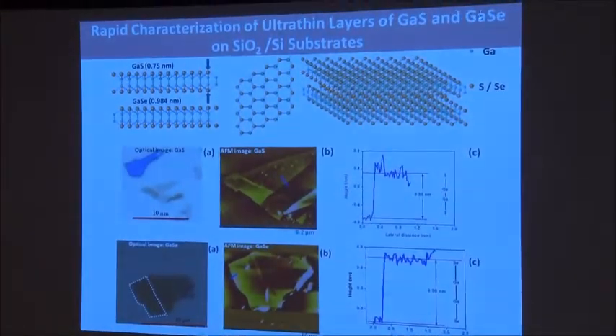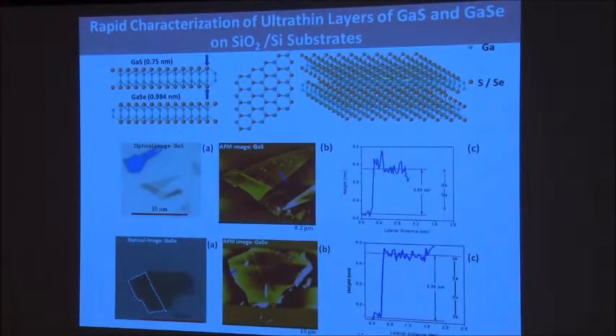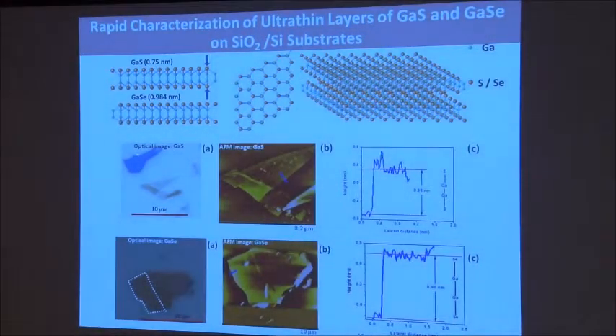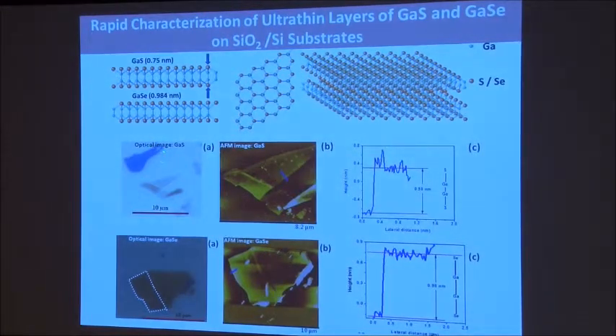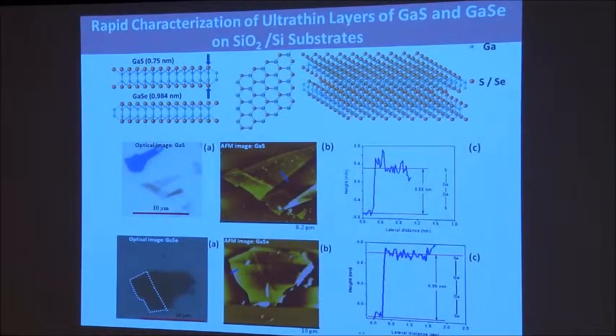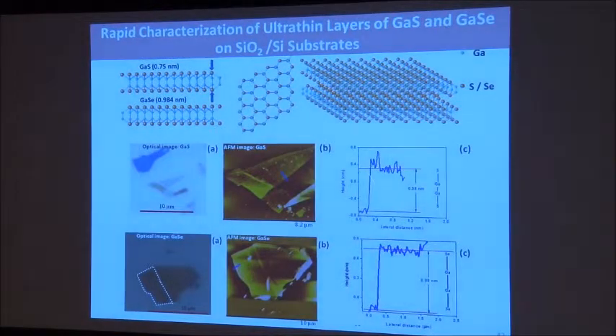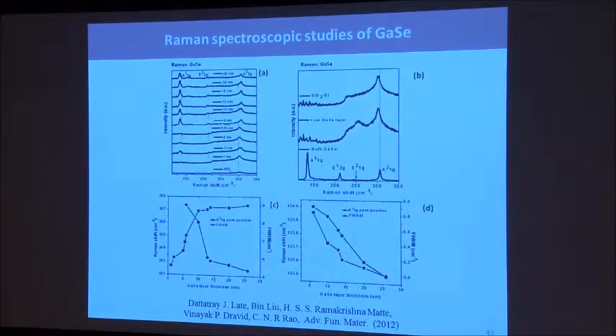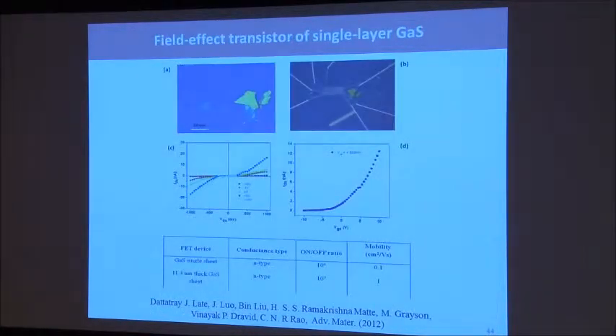Gallium sulfide, gallium selenide are also just like graphene. We have made transistors out of that. You can see that blue chip, there is a single layer gallium sulfide, single layer gallium selenide. We can measure the thickness of these things, study the Raman spectroscopy. All these we see as a bunch of layers. What happens to Raman spectroscopy, how one Raman mode stiffens, another softens, and so on in these materials. We have done all that with gallium sulfide. Then we have made transistors out of gallium sulfide and gallium selenide and studied their transistor properties as well.